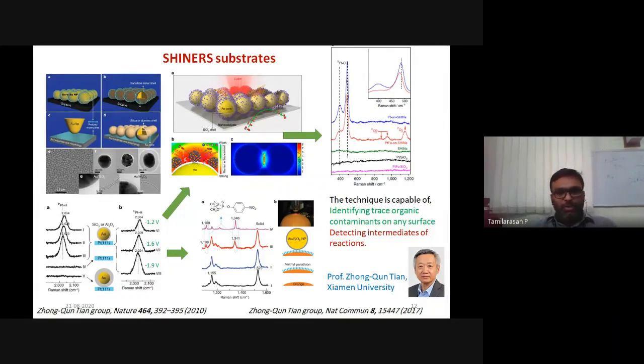And they have also demonstrated an application for this study. They wanted to find out the presence of methyl parathion, it's a pesticide, on orange. So they took a Raman spectrum of orange, and they took a Raman spectrum of methyl parathion also. So methyl parathion gives a peak somewhere around 1346. If you have methyl parathion on the surface of orange, then you will expect a peak here. But in normal Raman spectroscopy, it was not observed. Only when you put a SHINERS particle, you are observing this peak. So this is the potential of this technology, and they have extended the application of this substrate to other work also.